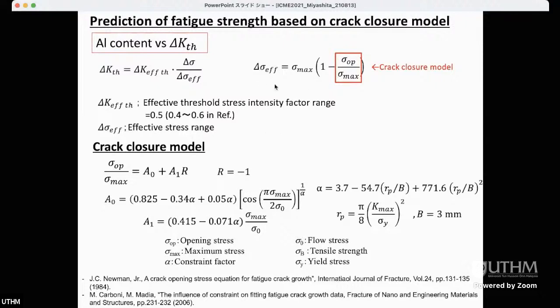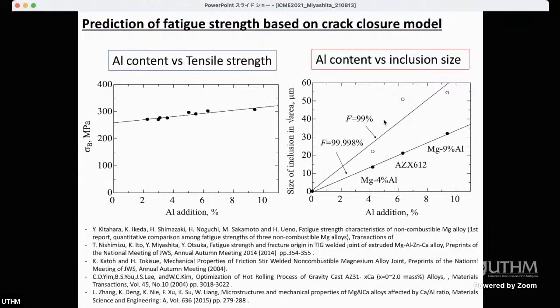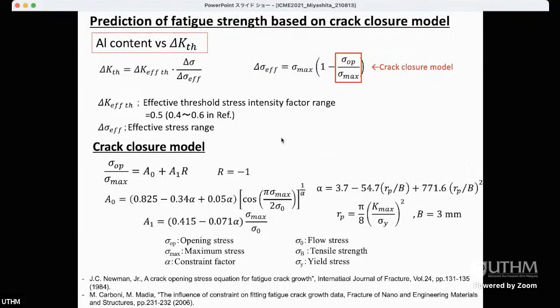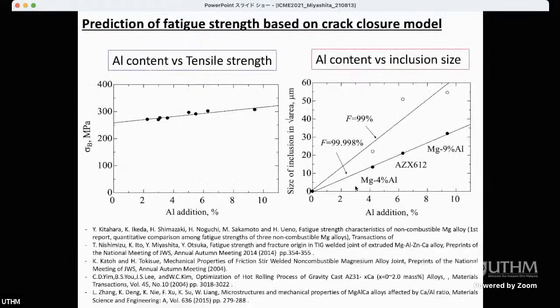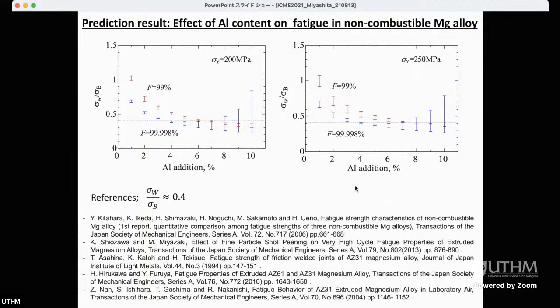So this is showing us these figures. Here we can predict it based on the crack closure model. And we took data from the reference, for example, the effect of aluminum content on tensile strength, and we could get this kind of line. And also we can predict the size of inclusion from this figure, which shows the relation between inclusion size and aluminum content. By using this figure, the experimental result, and the equation based on the crack closure model, we predicted the fatigue strength ratio.